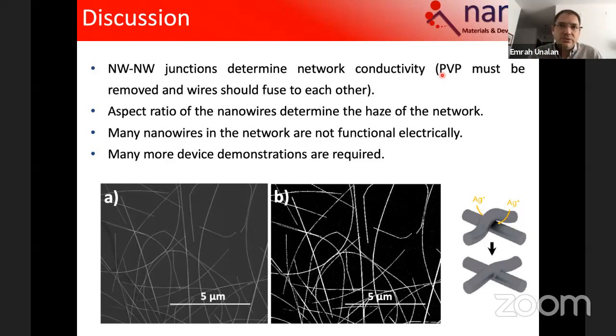So with the purification, we try to get rid of as much as we can, but not to 100% extreme, right? Because we make use of PVP for dispersion before spin coating. So that is number 1. Number 2 is the fusing, right? So I need to get rid of the PVP, plus I need to fuse the wires to each other. So this is still a very important issue that needs to be taken care of.